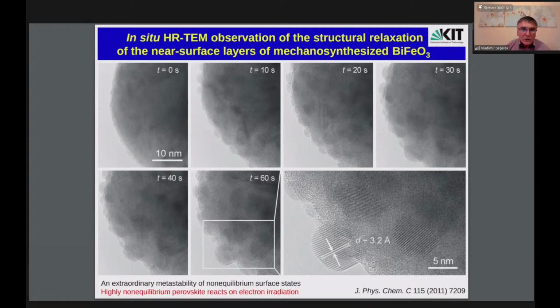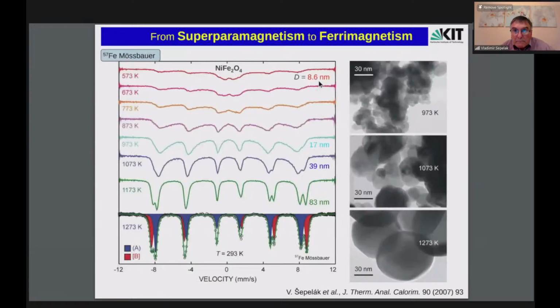That means transition to the more stable equilibrium state, and during heating of magnetically ordered nanoparticles, like in the case of nickel ferrite, we have a disappearance of superparamagnetism and the transformation to the ferrimagnetic state, as observed by Mössbauer spectroscopy in conjunction with transmission electron microscopy. You see growth of nanoparticles from nano to some larger size, and simultaneous disappearance of the superparamagnetic state.